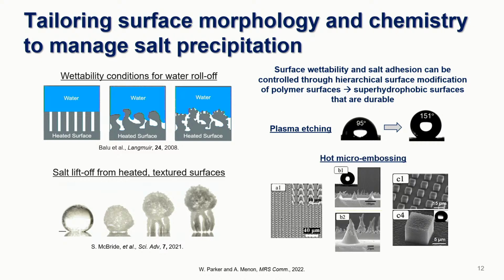The other technique that we're employing, because we're working with these polymers, is micro hot embossing. And so with this, we can essentially create a mold, and then you transfer the pattern from the mold to your polymer surface. And so we can create these cone or pillar-like structures, and we can adjust the distance between those pillar structures. We can adjust the height of the pillar structures, or we could make these pyramids, cubes, all sorts of different patterns, and we can really play around with the spacing and the height in order to give us this desired behavior, which is we want the water to roll off and we want the salt to